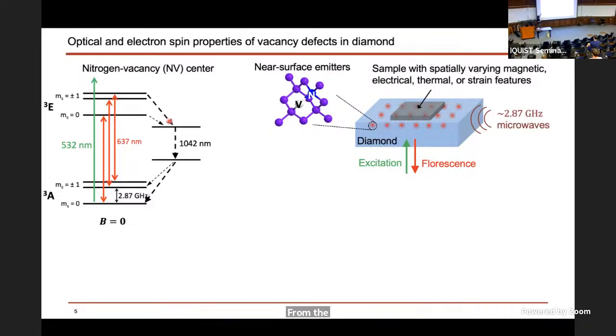So a common operation involves just continuous excitation of this energy system with a green laser. Through many, many cycles, because of preferential non-radiative relaxation of the electrons back to the ground state, ms equals 0, you have polarization of the NV center at ms equals 0. This is also the mechanism by which you have optical readout that is dependent on the spin state, namely that you get more fluorescence if your spin is at ms equals 0 versus ms plus or minus 1. So this ground state is also useful for sensing.